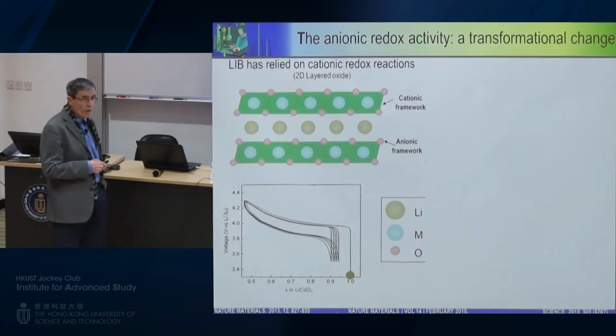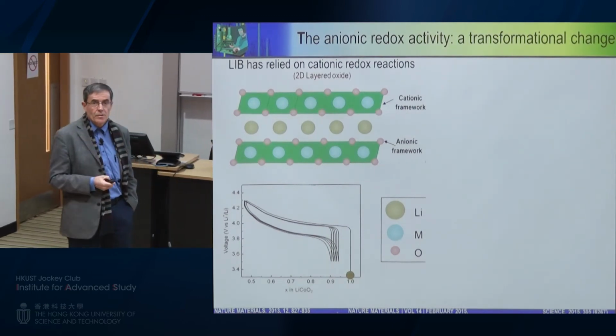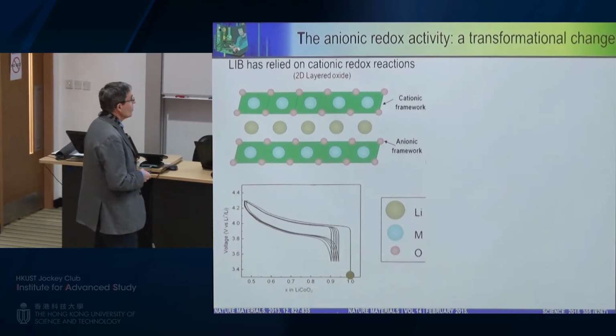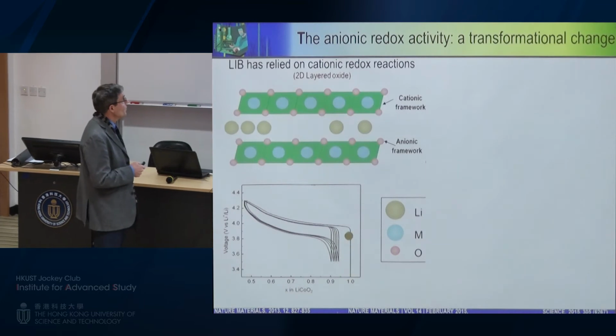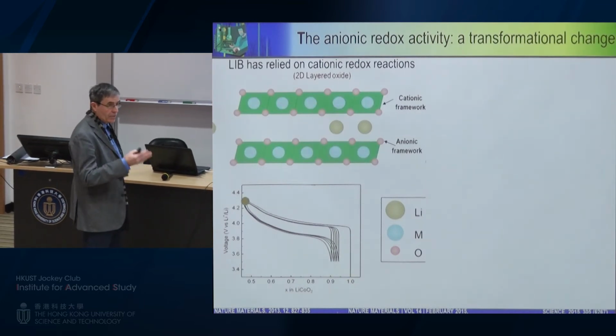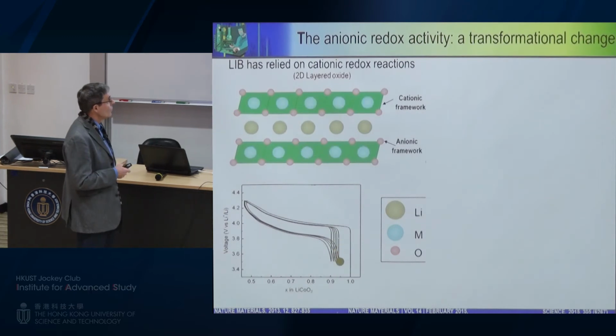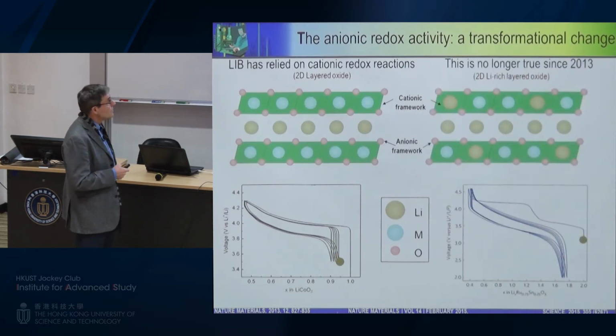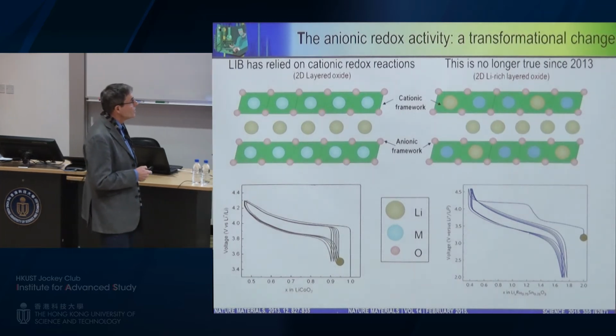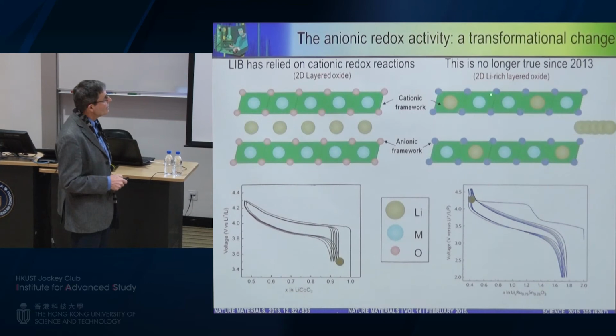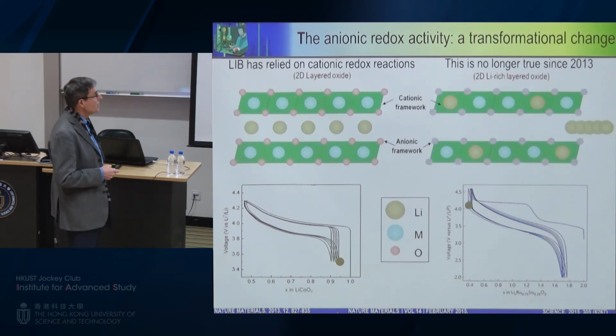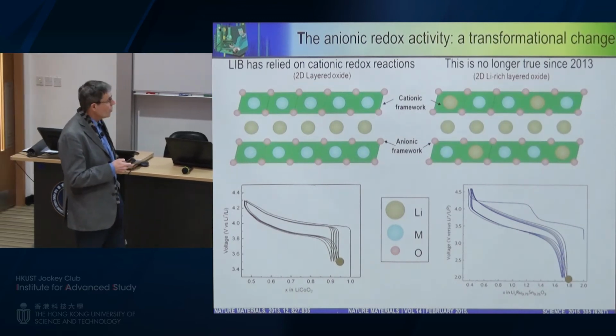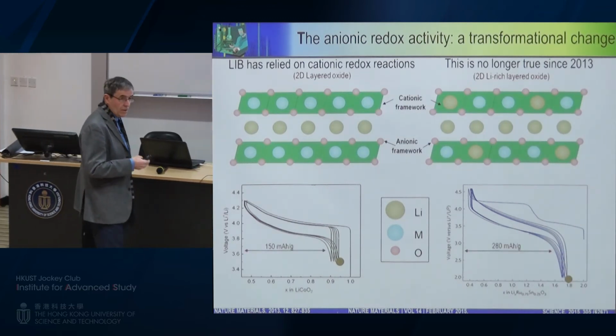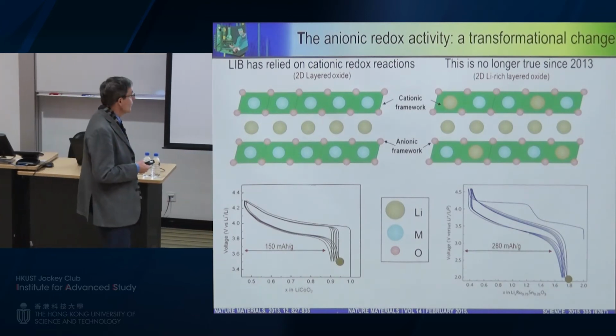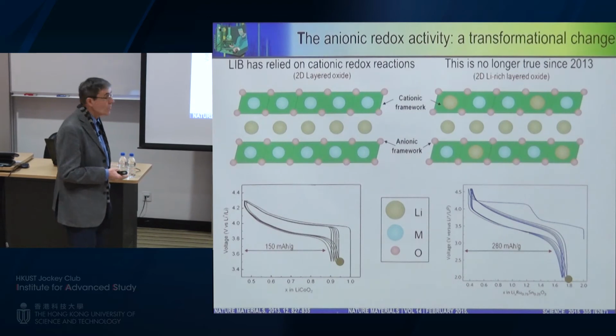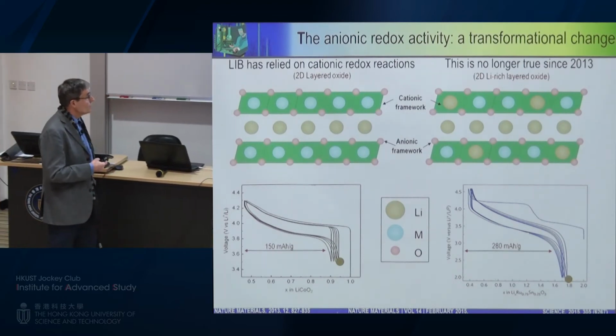Indeed, this is the way that lithium-ion cathode materials have been considered for 35 years. It means that when you remove lithium, as you can see here, only the cations are acting as a redox couple. Now, what I showed you is that if you look at these new materials, when you remove lithium, the cation and the anionic network both participate in the process. And the advantage of all of this is that we can double the capacity, going from 150 to 280. So this is more or less the paradigm we come out with.